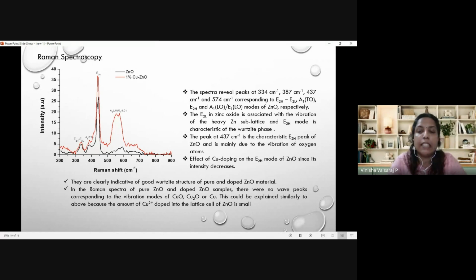We characterized the material with Raman spectroscopy, and here we can see the different vibrational modes of this material. This indicates a good wurtzite structure of pure and doped ZnO material, because there are no peaks corresponding to the vibration modes of copper, copper oxides, etc. So that confirms the successful doping of copper into the lattice of the ZnO.